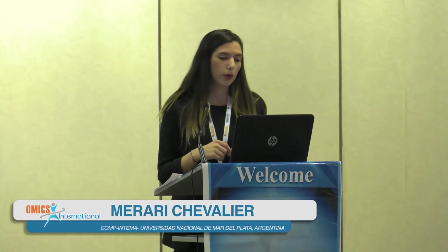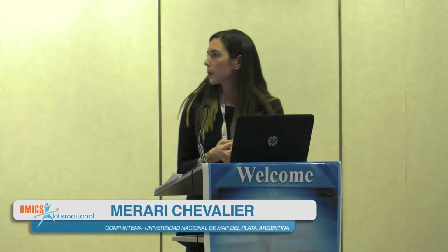Well, regarding this protein, as I said, as we tested BSA, we decided to continue testing some hydrophilic agents. In this case, we started to work with polylysine-loaded PLA and PEG-PLA microparticles. We used a blend of polymers, PLA alone and then the copolymer with PEG. The objective was to study this kind of peptide. This was a polylysine of 10 units, because in our group we have a collaboration that involves peptides for anti-cancer treatment. As these peptides are really expensive, we decided to use polylysine as a model.